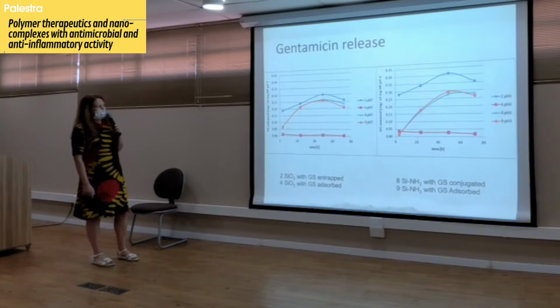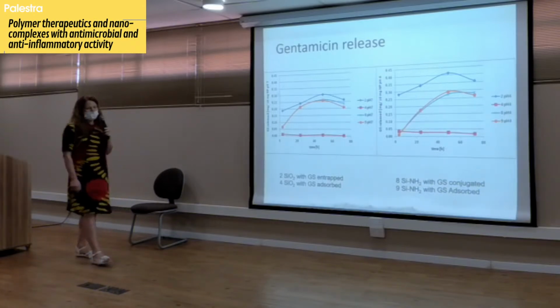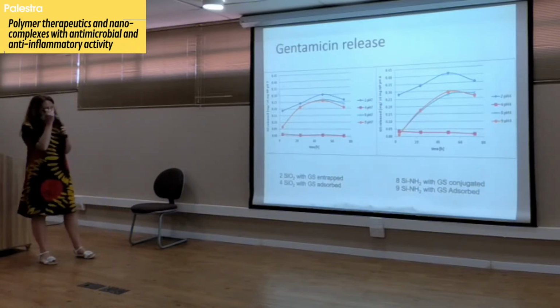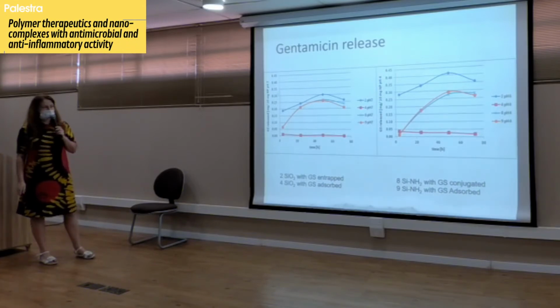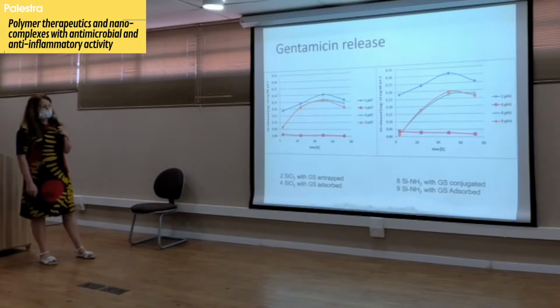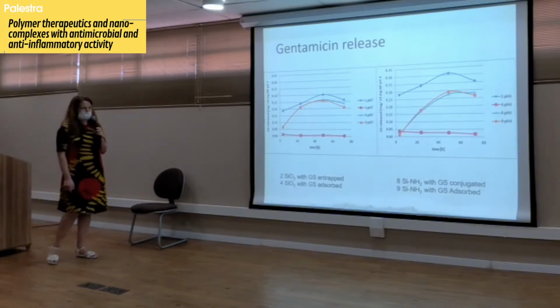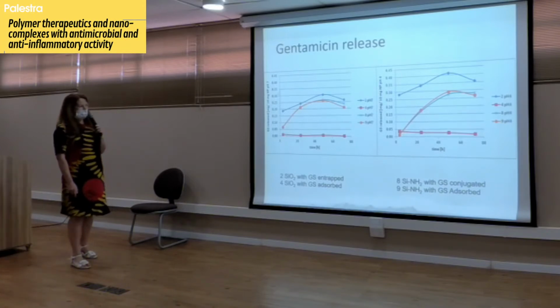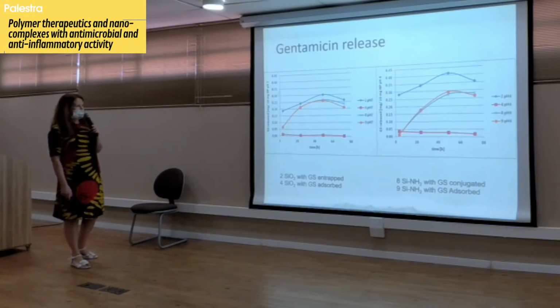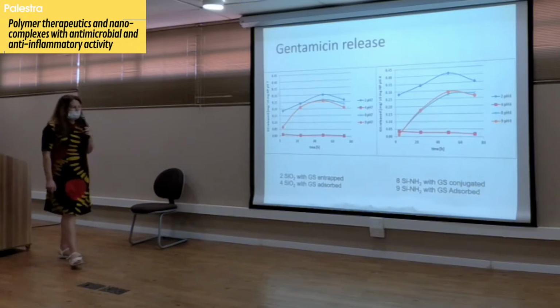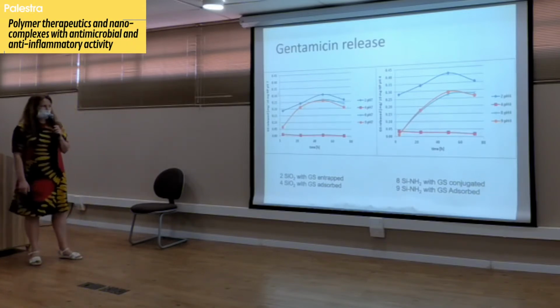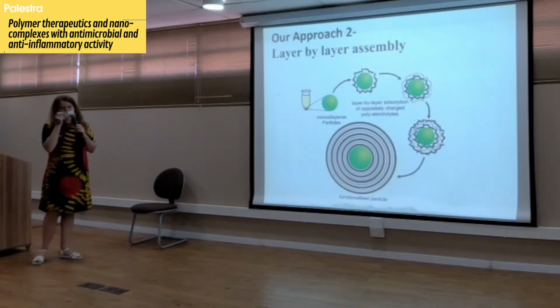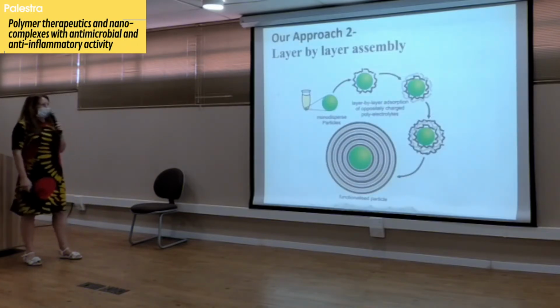As you can see, pH also influences release, because pH 7 is a neutral pH, and when we have an infection, our pH drops. So we wanted to simulate what will happen inside when we have an infection. So release changes as well. But it's not an impressive release. We wanted to achieve much longer and more controlled release. So we wanted to change our strategy, and we did change our strategy.